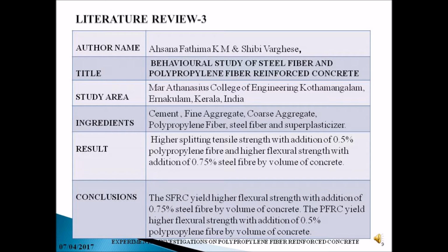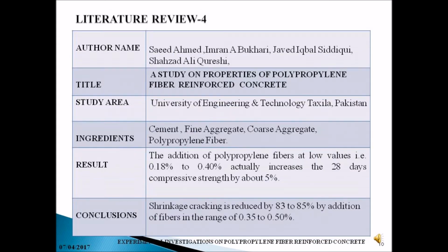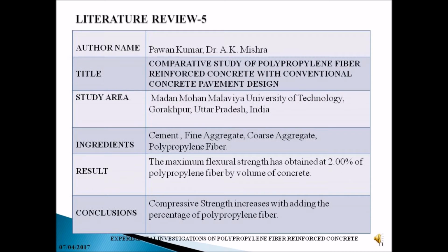Literature review 3 is Behavioral Study of Steel Fiber and Polypropylene Fiber Reinforced Concrete. Here two types of steel fiber and one type of polypropylene fiber are used. It is concluded that high split tensile strength is achieved at 0.5% of polypropylene fiber. Literature review 4 is titled A Study of Properties of Polypropylene Fiber Reinforced Concrete. The results are: addition of polypropylene fibers at lower values like 0.18 to 0.40 increases its compressive strength by 5%. Shrinkage crack is reduced.